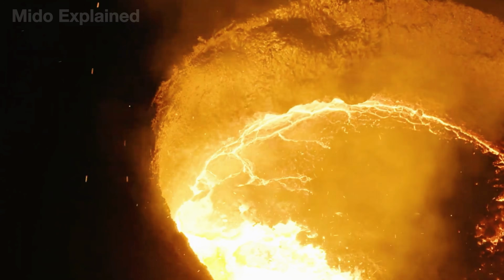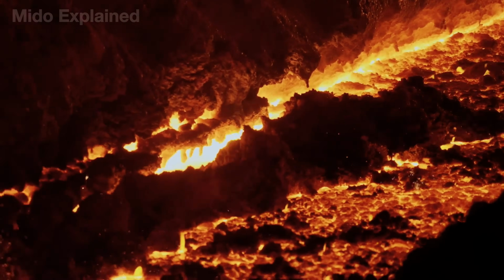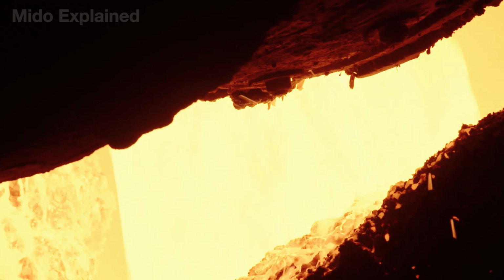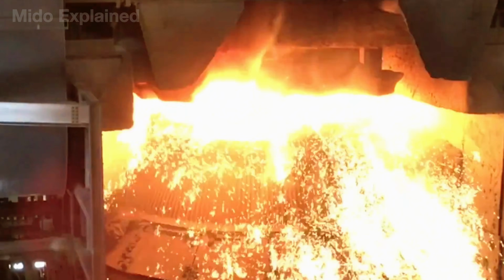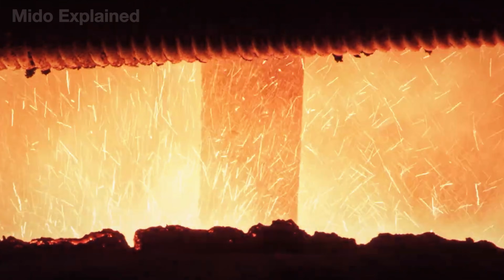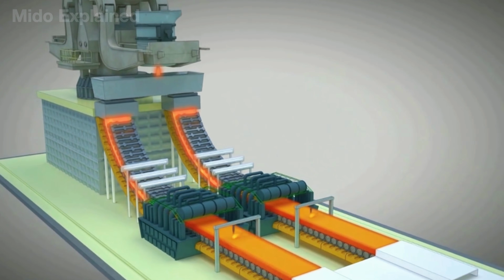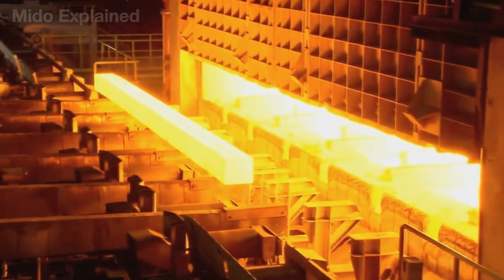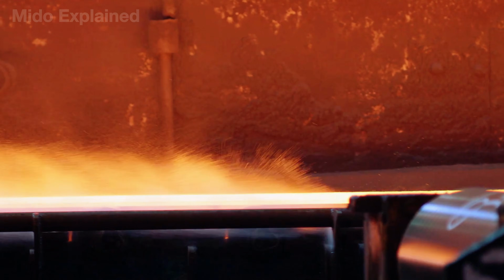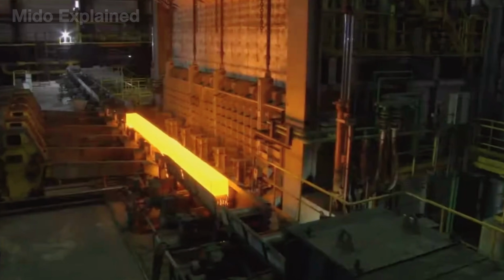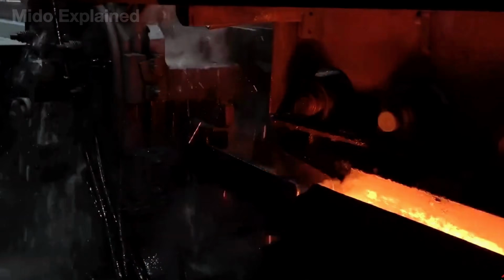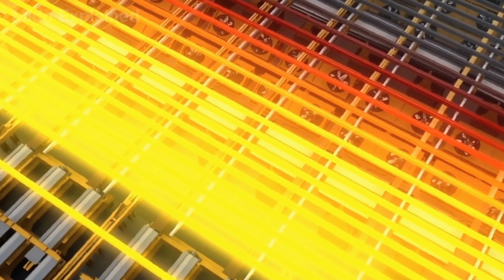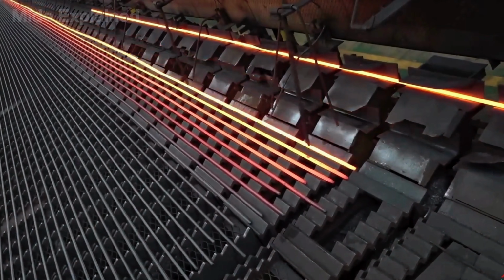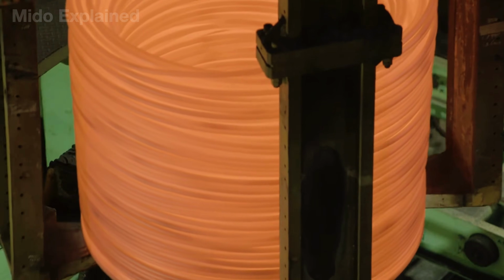After being molten, the material is still far from the shape of a nail. Instead of being poured into individual molds, the molten steel is fed into a continuous casting system, where it flows through water-cooled molds and solidifies into long steel billets. These billets are then cut to standard lengths before being transferred to a hot rolling line. Here, they are reheated to approximately 2,100 degrees Fahrenheit, and then pass through more than 20 consecutive rolling stands. Each time they pass through a pair of rolling mills, the cross-section of the billet shrinks until they become steel bars only about 0.22 inches in diameter. Upon exiting the line, they are coiled into coils weighing over 2 short tons, ready for wire drawing.